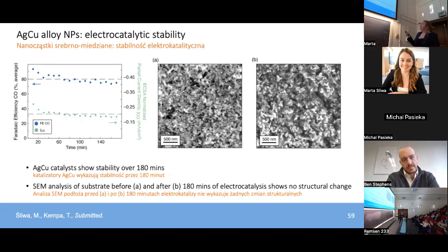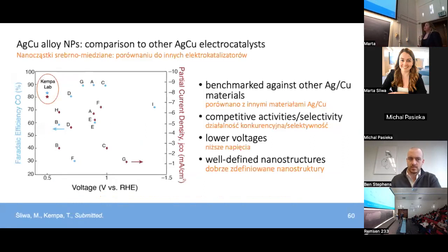We also imaged the surface of the nanoparticle substrate both before and after the 180 minutes of catalysis, and that revealed no apparent surface or structural change or visible material loss. So again, not only are these alloy nanoparticles well performing, but they're also stable. We also benchmarked the performance of our 5% copper and silver alloys to other materials that contain silver and copper for electrocatalytic reductions. Our 5% copper alloy is able to achieve competitive Faraday efficiencies close to 84% compared to other referenced examples. But it's important to note that we are able to do this at relatively more mild potentials, where these examples are bumping up to a little bit higher than our Faraday efficiency, needing much more negative voltages to be applied. And also, as we saw in previous studies, the nominal copper loading is not what we actually calculate. So we're able to achieve these activities at even lower copper than what we thought, which is super